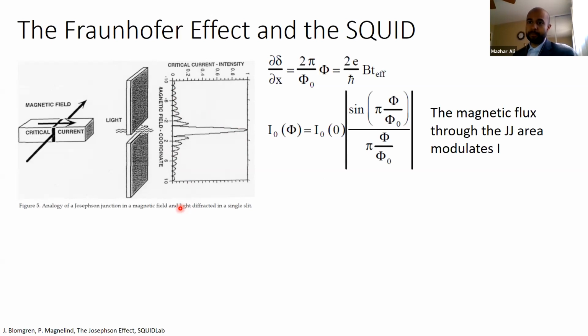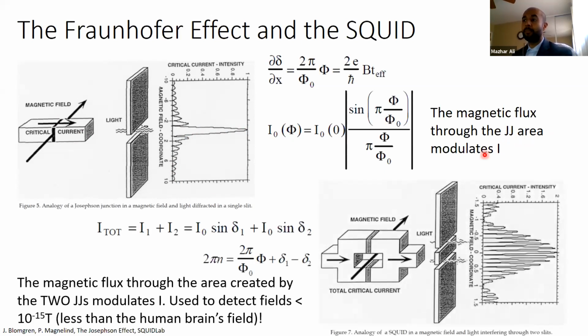So if you have a junction and you want to see if it's really a Josephson junction, one of the most important experiments to do is to measure the critical current versus magnetic field dependence and see if you have basically a single slit diffraction, so a sinusoidal dependence in roughly a 1/B envelope. This is important because the entire junction is very, very sensitive to the magnetic flux through the junction. And entertainingly, even more sensitive than one junction, maybe kind of obviously, is two junctions, for example, in parallel. This is the SQUID, which is two Josephson junctions connected in parallel, and it's exactly analogous, as you'd expect, to a double slit diffraction experiment.